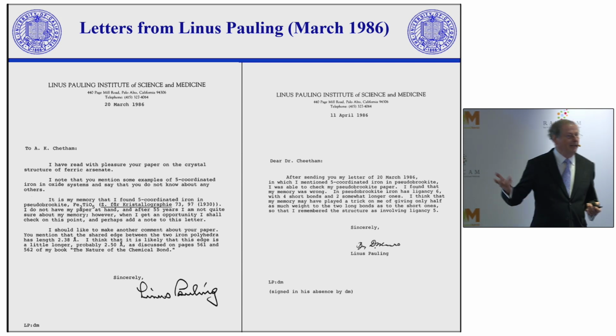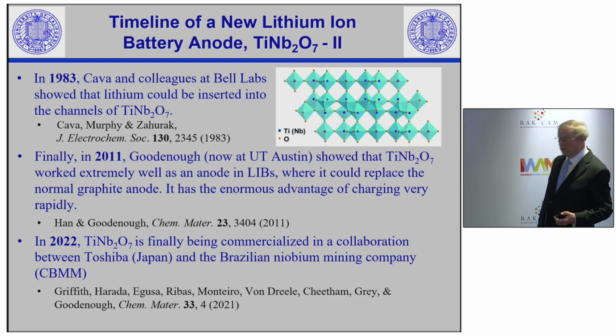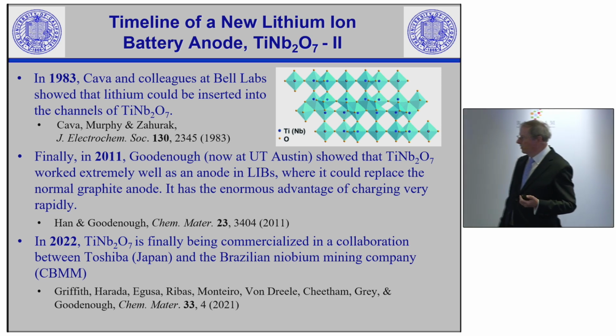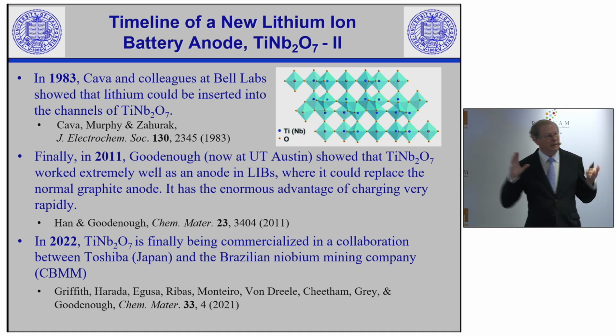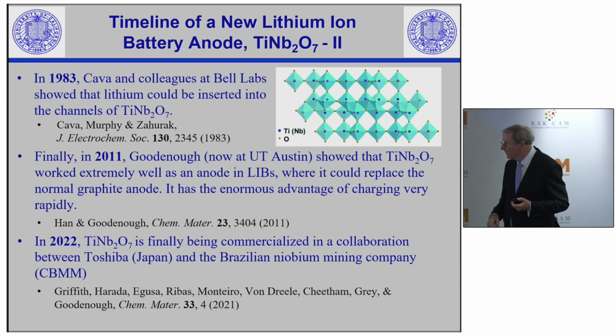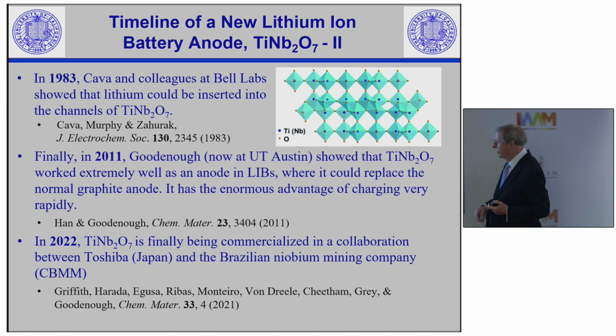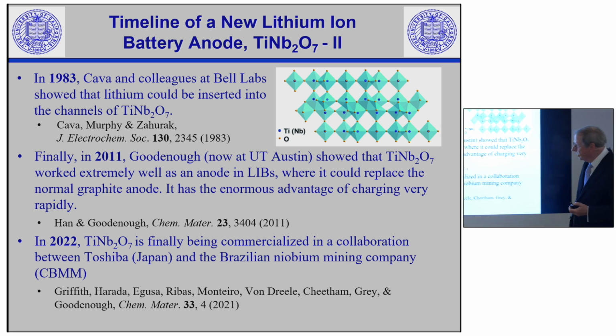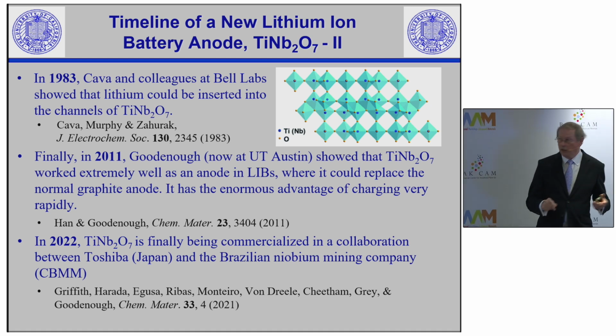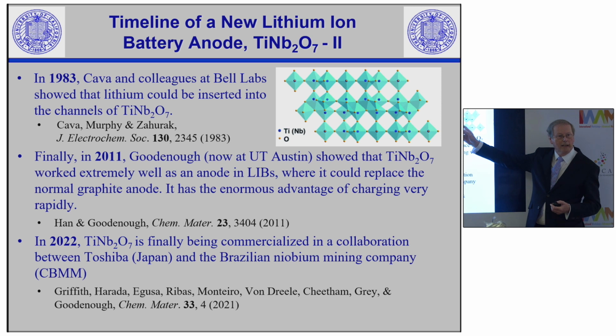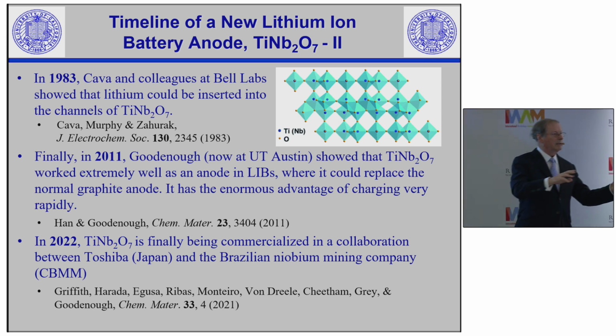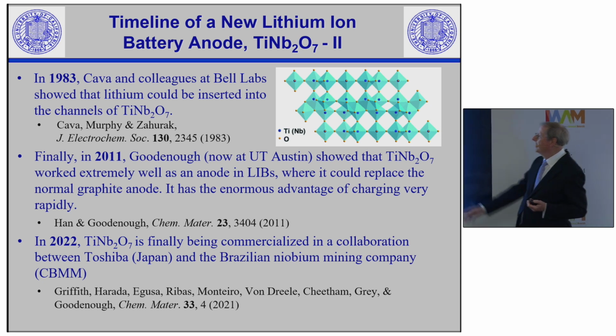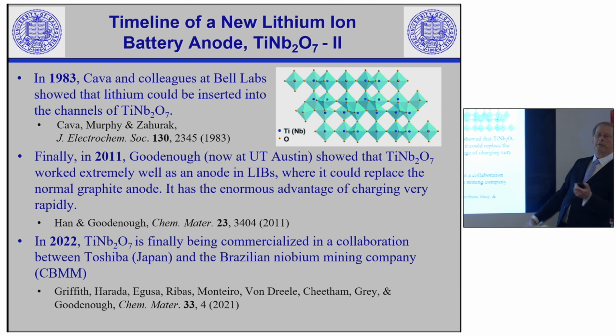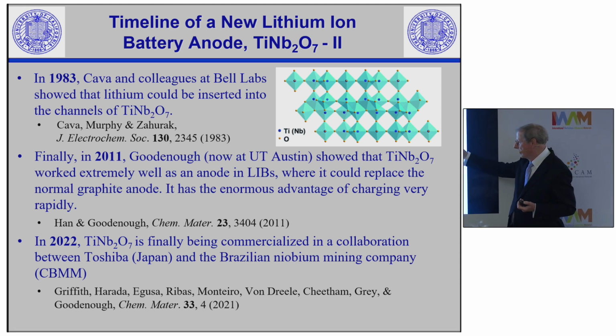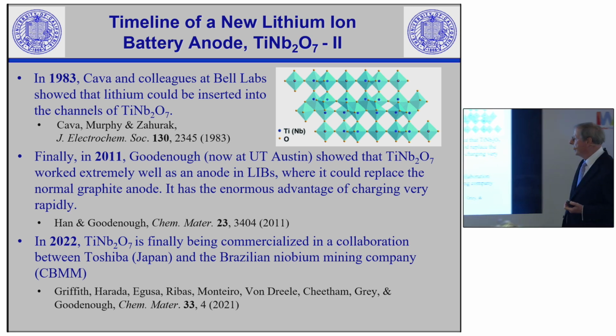So let's go back to the anode. This is just a segue, this titanium niobium oxide. So we'd looked at it in '74. Then in 1980, John Goodenough and others basically launched the rechargeable lithium battery. But this was not a candidate to use in the battery at the time. But then in '83, a few years later, Cava and colleagues at Bell Labs showed that you could actually put lithium into the channels of this structure. You could insert lithium. And that's where my titanium niobium distribution became important, because it has an impact on the lithium diffusivity. And then nearly 30 years later, John Goodenough again pops up, and he shows that this titanium niobium oxide works really well as an anode in lithium-ion batteries.